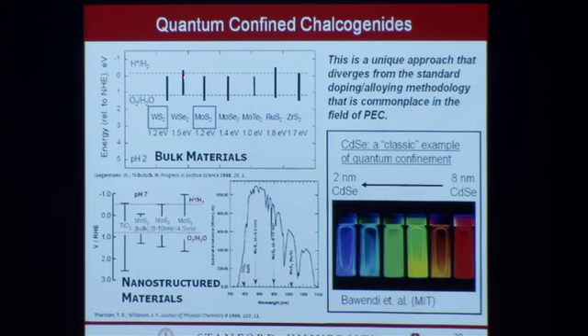Also, you can see that the band placement is not ideal for the valence and conduction band, but it's close enough such that a little bit of quantum confinement should get you to be able to straddle those bands. So we looked at these, and tungsten sulfide and moly sulfide really stood out to us because they're very earth-abundant elements. They're also known to be good hydrogen evolution catalysts. So we said to ourselves, well, if we can get these semiconductors to absorb a good fraction of the solar spectrum and pump electrons into that surface, they should be good catalysts as well to turn over H+ to H2.